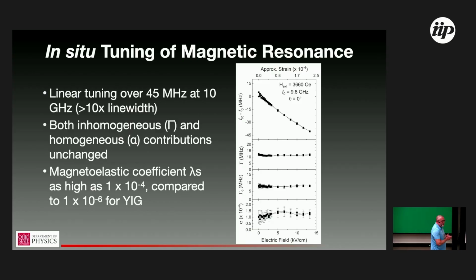I put these slides up on Monday, for those who may feel some deja vu, but just to talk through it again. In this stack, I apologize if some of these axis labels are a little too small to read. I couldn't figure out how to fit this bigger on the slide. At the top, we have the resonance frequency tuning as a function of applied electric field. Critically, the total line width, the inhomogeneous broadening, and the alpha do not change. So we can strain it and nothing bad happens. And we did a first order failure analysis of a few hundred cycles. Didn't see any change there either.